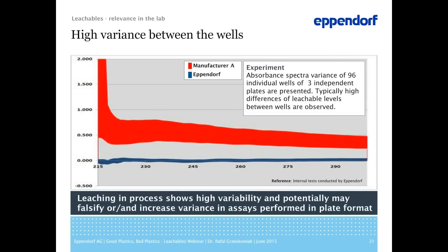In this graph, the broad red line represents a variance of 96 individual wells of 3 independent plates, and is indeed very high. This indicates that the leaching process shows per se very high variability and potentially may falsify or increase variance in assays performed in plate format. So it literally means that depending on the position of the well, different levels of leaching may occur, and therefore different effects on the assay may take place. It might be of tremendous importance for all those who work with different layouts, dilution series, or similar plate position dependent assays, for example in drug discovery.